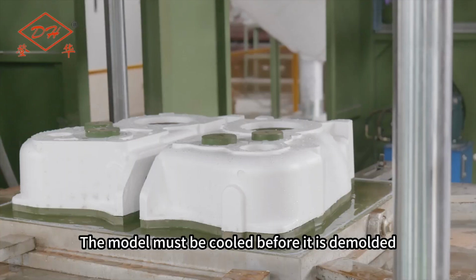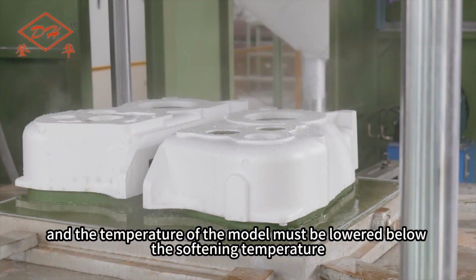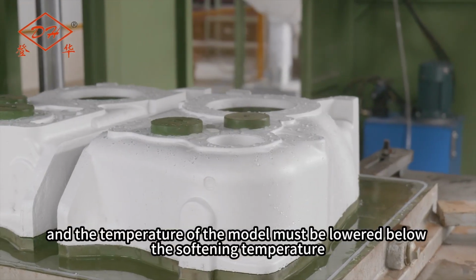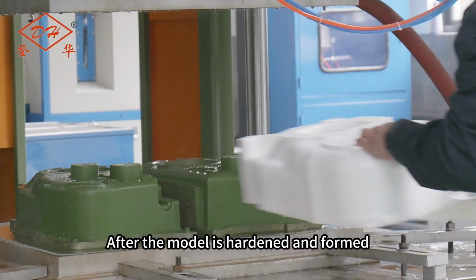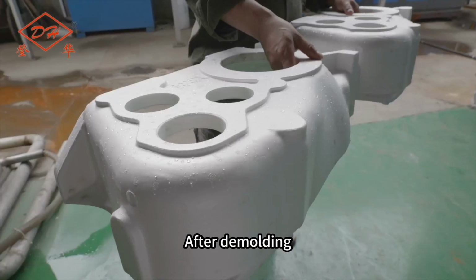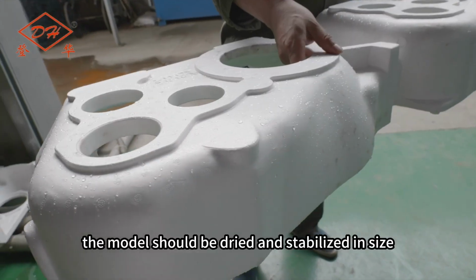The model must be cooled before it is demolded, and the temperature of the model must be lowered below the softening temperature. After the model is hardened and formed, it can be demolded. After demolding, the model should be dried and stabilized in size.